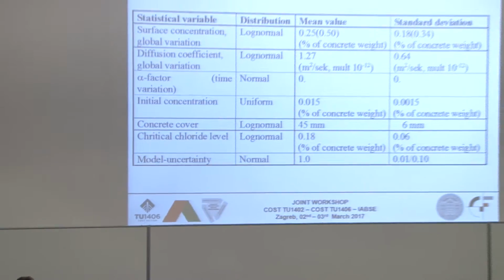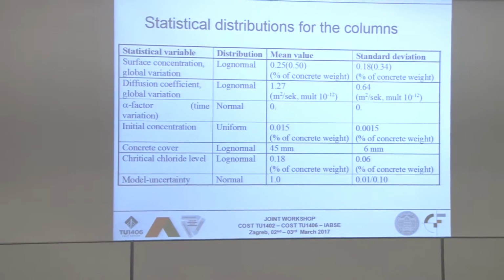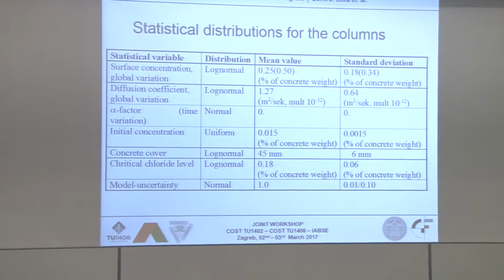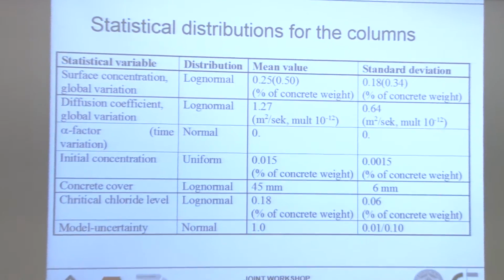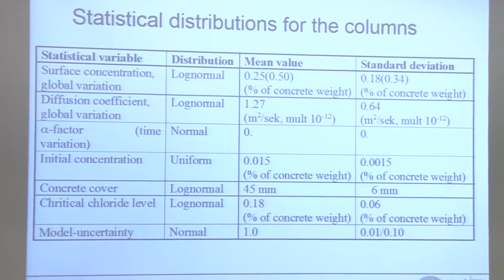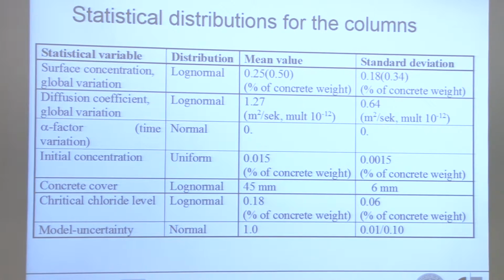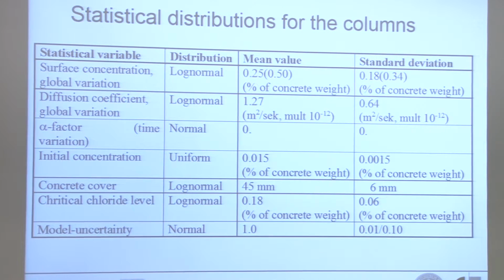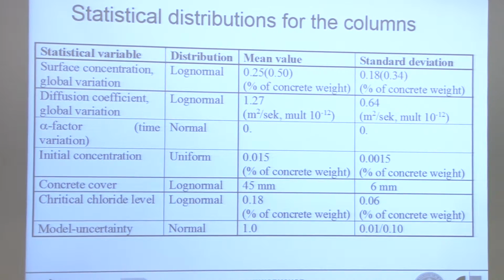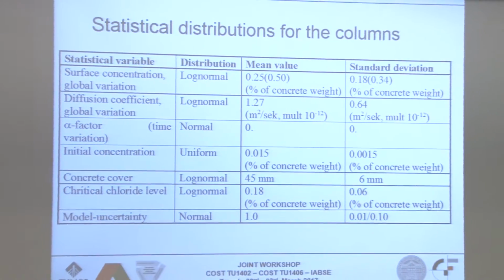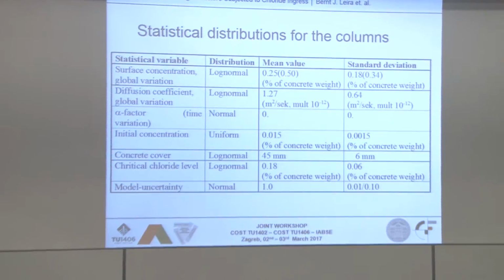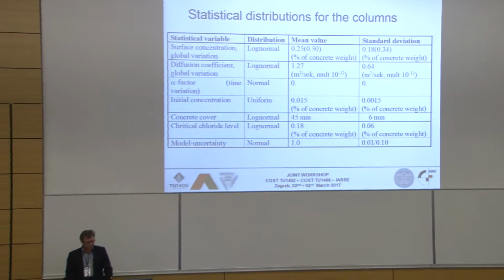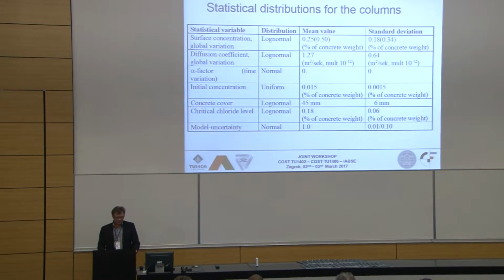Now for the columns, also we have a similar table. I will not go into it because the results I will show are for the superstructure. But again, you see that we have two values for the mean values for the surface concentration. This corresponds to the two different columns, 0.25 for one of them, and then twice as high for the other one, 0.5. Also the standard deviation is very different, but the COV is pretty constant.